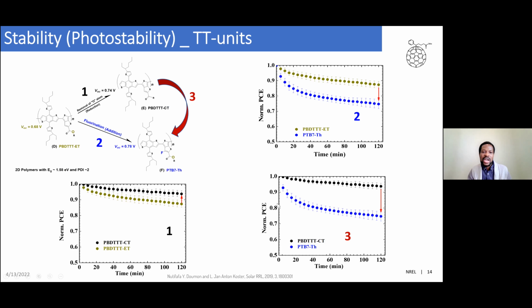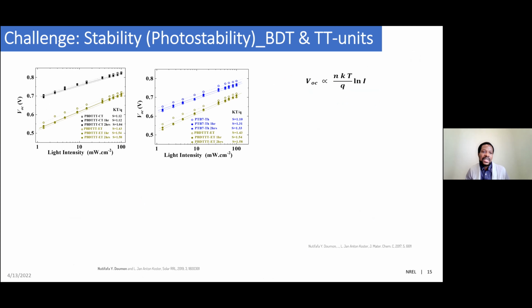So in this case, we have contradictory results: some of the changes that we have observed in the TT unit result in both improvement in efficiency and stability, but the other change results in improvement of efficiency but is bad for device stability. So we look at light intensity dependent measurement, because that gives us an idea about what is happening in the system. And with the ideality factor, we can see how they progress over the exposure time. You can really see what the charge dynamics in the system are.